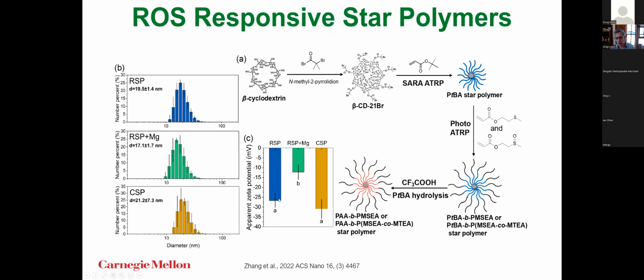They're negatively charged. When we load it with magnesium, they're a little less negatively charged, which makes sense because we're putting a positive charge into the core and offsetting some of that charge. We also made a control polymer that doesn't scavenge any reactive oxygen, but it's similar in size and charge to the reactive one. So we wanted to compare a reactive one to a non-reactive one. And you can sort of see here, this is the size distribution. They're all quite similar in size.